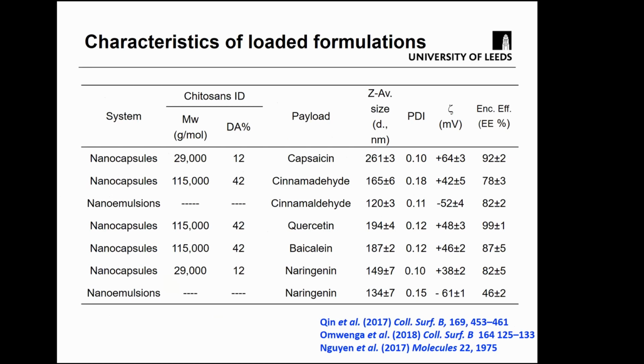As I said, invariably we can obtain coated nanocapsules, and as we can see here for different payloads ranging from the ones I've mentioned before, the encapsulation efficiency is almost always very high, above 80%. Nanocapsules will invariably have a highly positive zeta potential, whereas the nanoemulsions will always have a highly negative zeta potential. Their size is another feature of these systems: it is very conserved, normally around 200 nanometers. This is due to the spontaneous emulsification process by which these emulsions are obtained.